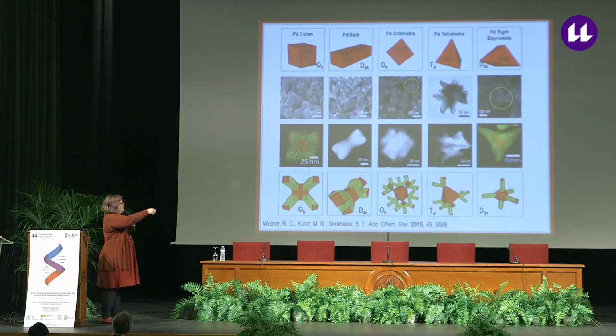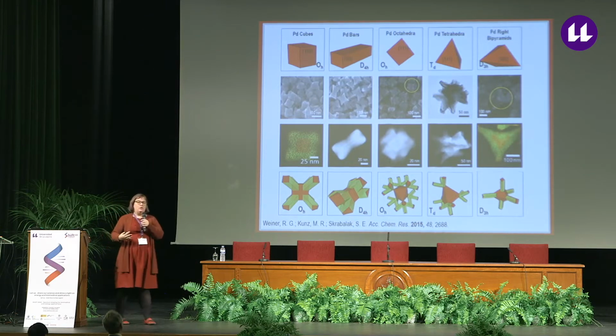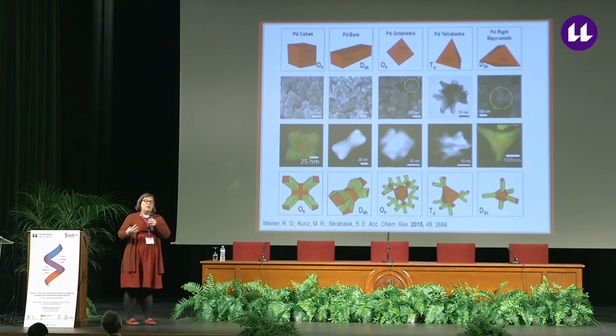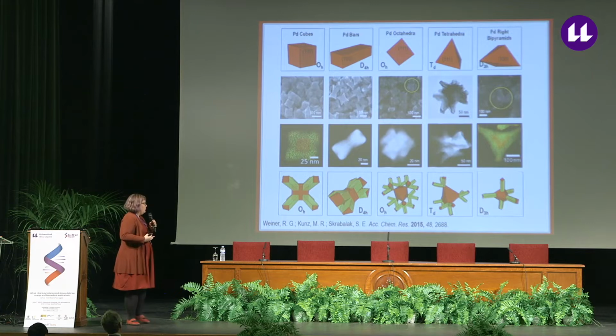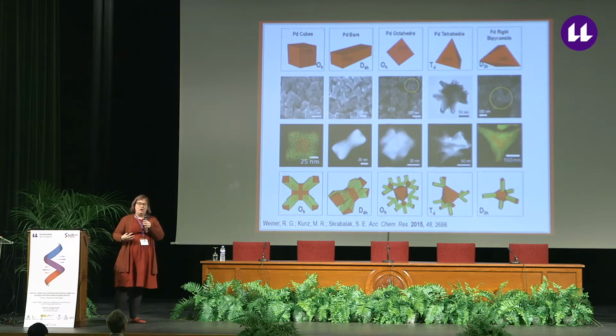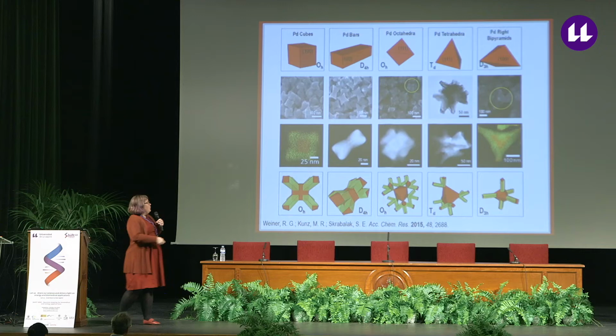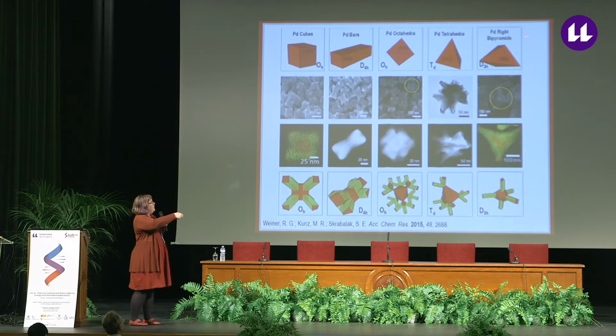If we look at palladium tetrahedra, we have 3 branches emerging per vertex of our seeds, but the overall structure has tetrahedral symmetry because the branches are proceeding along the 1-1-1 directions. And so the number of branches that are being observed corresponds to the number of 1-1-1 directions that can protrude out from the seed rather than back into the seed volume. There's one exception to this, which is the case of the right bipyramids.